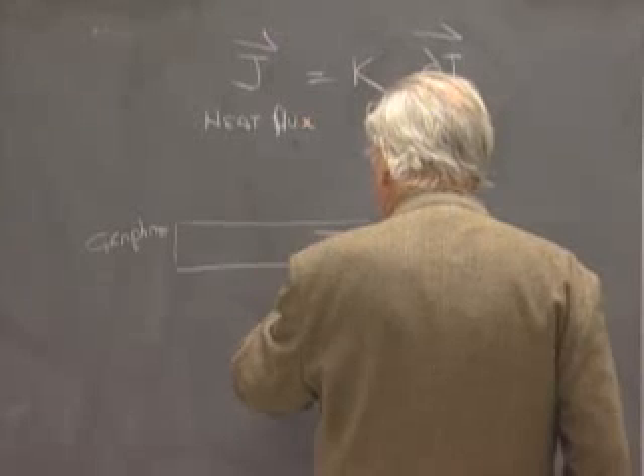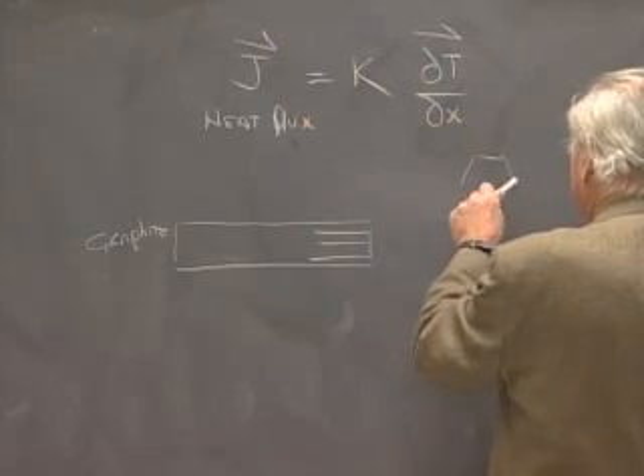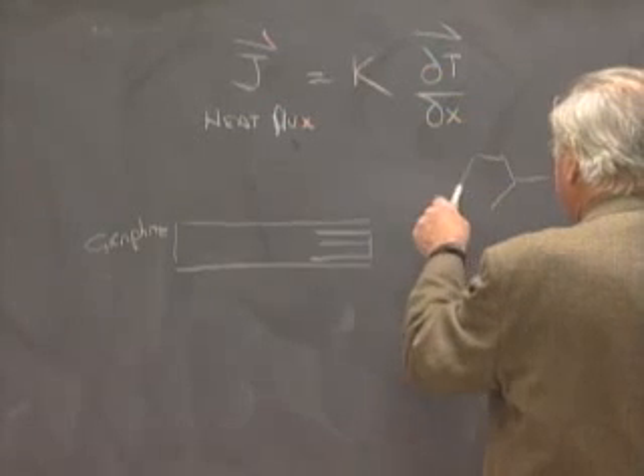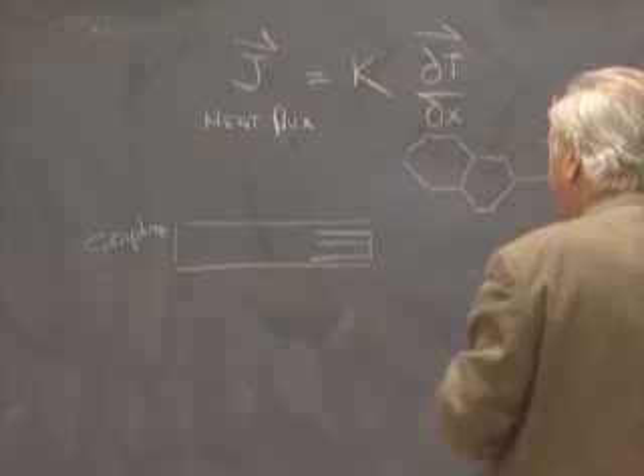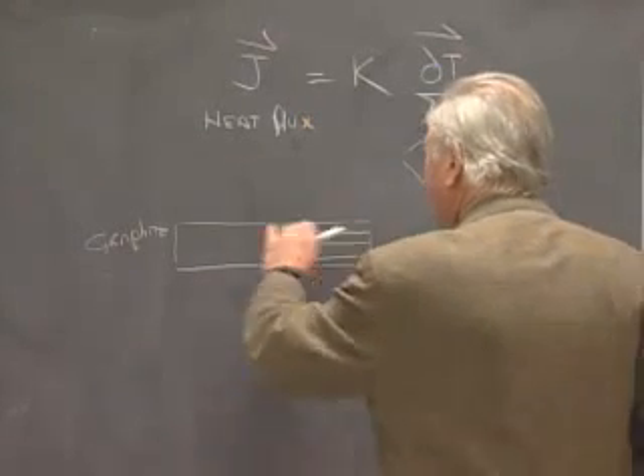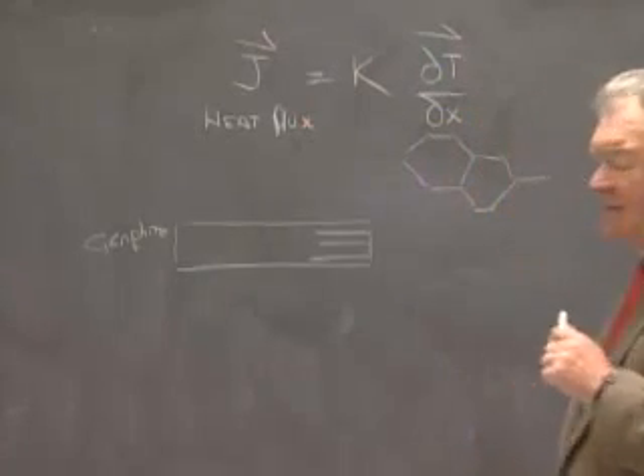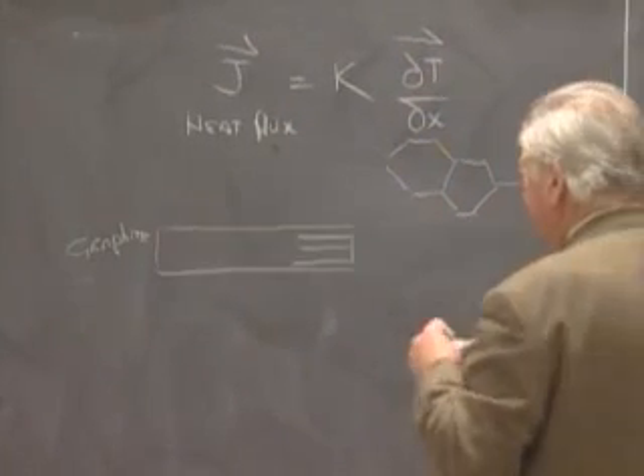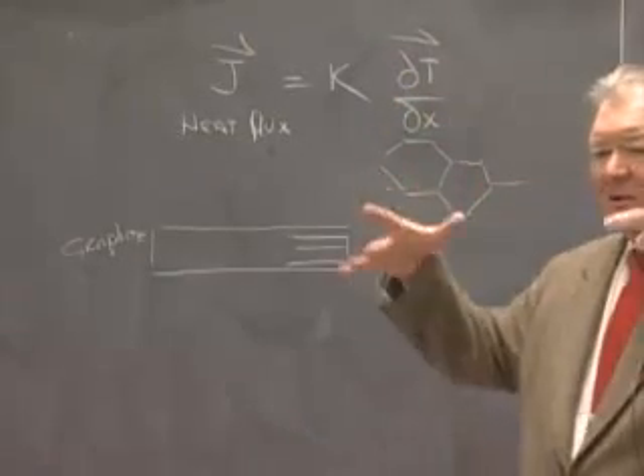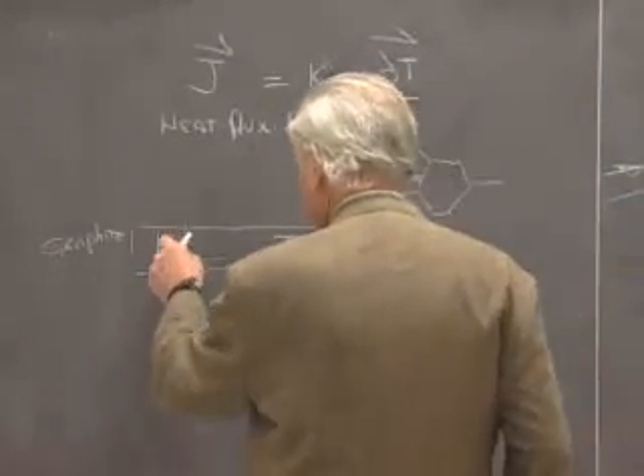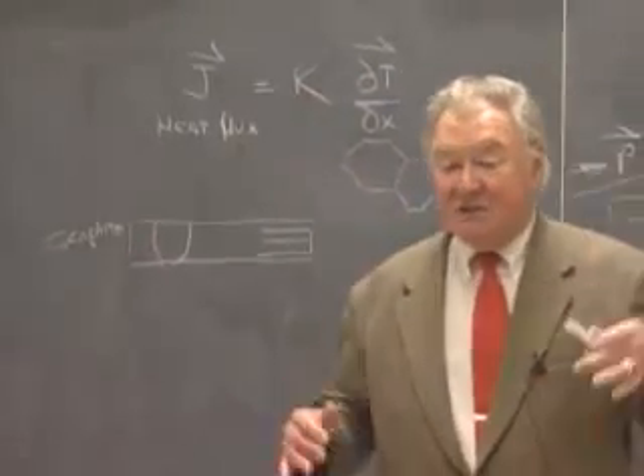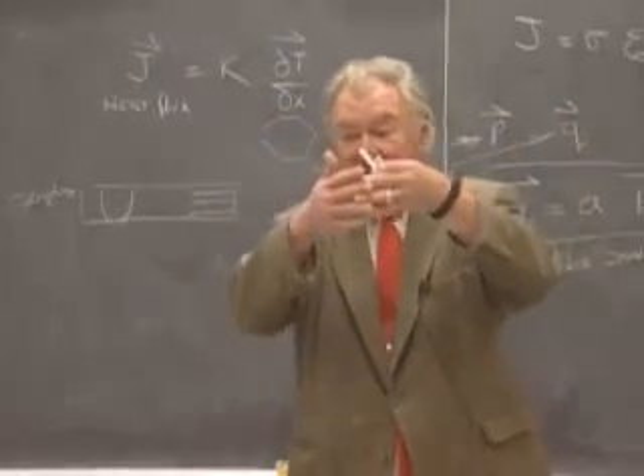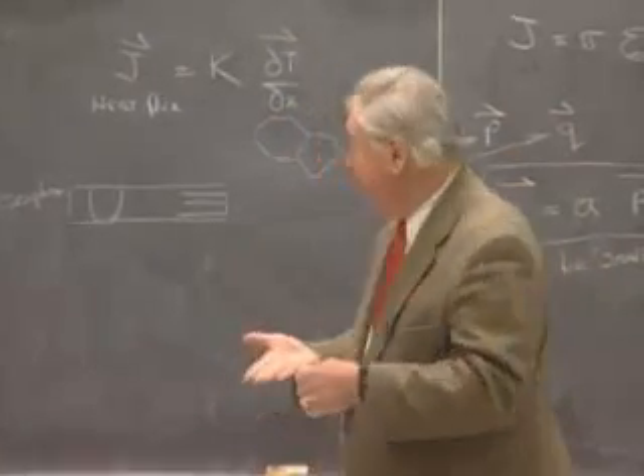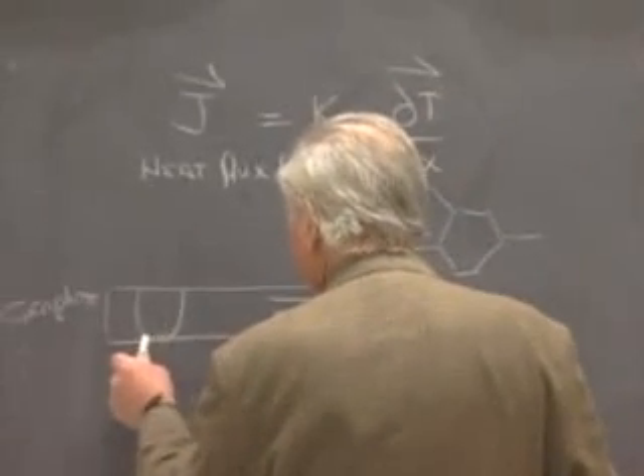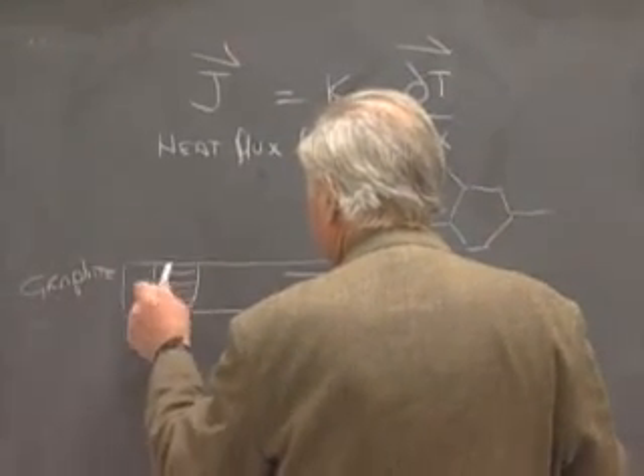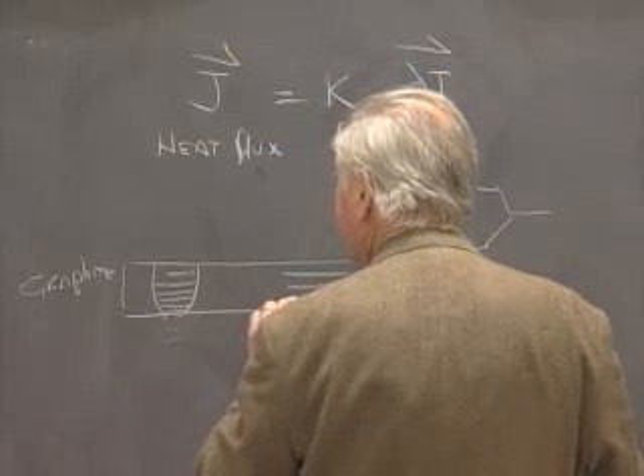And have the layers, the graphite sheets, which are hexagonal rings in which each carbon has 3 neighbors, and have the sheets be parallel to the surface of an extended 2-dimensional slab. Now, we can't do that. Single crystals of graphite don't occur in sizes like that, but what you can do is make a material called pyrolytic graphite that you make by having a reaction in a vapor phase and having the soot that's formed settle down onto a substrate. And what happens is you nucleate a graphite crystal in one orientation, and that grows preferentially with its layers parallel to the surface on which it's nucleated.